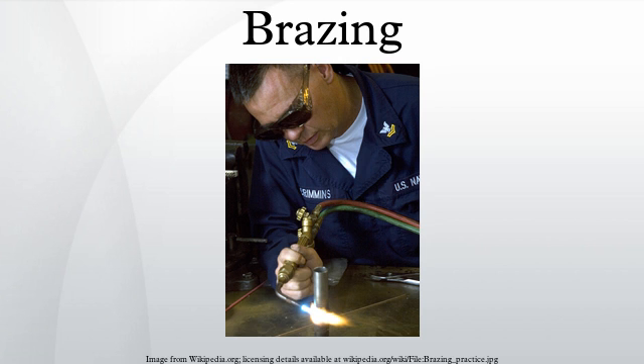The best temperature is usually selected so as to be the lowest possible braze temperature, minimize any heat effects on the assembly, keep filler metal-base metal interactions to a minimum, and maximize the life of any fixtures or jigs used. In some cases, a higher temperature may be selected to allow for other factors in the design.